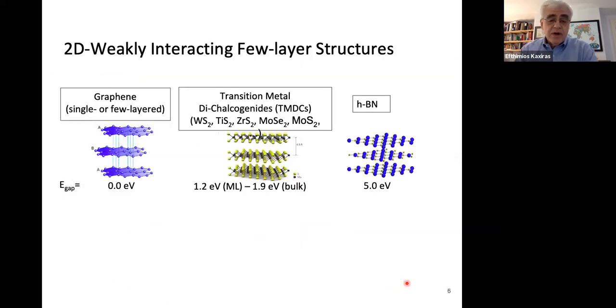So in our work, and in fact, in most groups working in this area, there are three very popular classes of materials. One is graphene, which is the metal that I mentioned. It has a zero band gap, and it can be in a single or a few layered structure. There is a very interesting family of semiconductors. They're called transition metal dichalcogenides, and they have different band gaps depending on the number of layers, monolayer or multilayer structures. They have different band gaps, and of course, depending on the composition of the material.